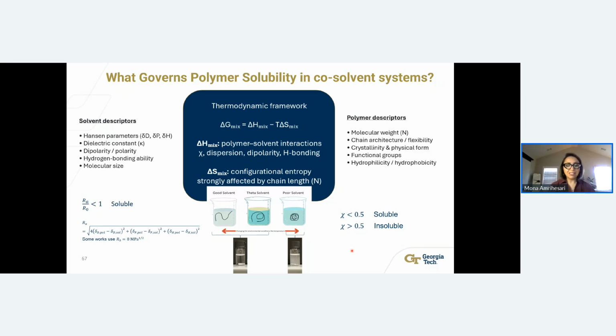But the challenge is that these are hard to get. We cannot experimentally get this interaction parameter. It is almost impossible. It's very time-consuming or expensive computationally to simulate these results. And the other challenge is that there is preferential polymer and solvent interaction that emerges in the mixture. Solvent properties do not always match up linearly, and a small composition change in the material can change the whole story. So can models that are trained in the single solvent system predict these emergent behaviors?